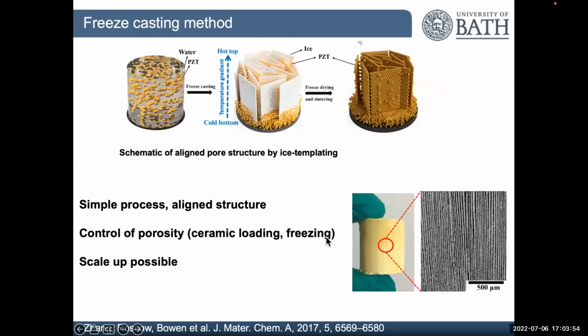And that's where the link with Professor Yan Zhang at Central South University comes in. She visited Bath as a Marie Curie fellow and introduced us to freeze casting, and that could produce these beautiful structures where you get exactly what we want, highly aligned pores within a specific orientation. We can now apply electric fields to this to align those dipoles, get very high polarization, high d33 values, but much lower permittivities because of the presence of the pores within the material.